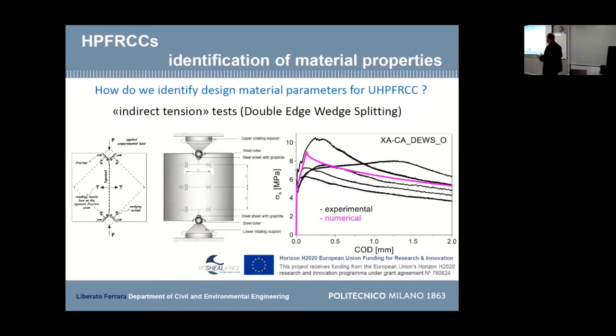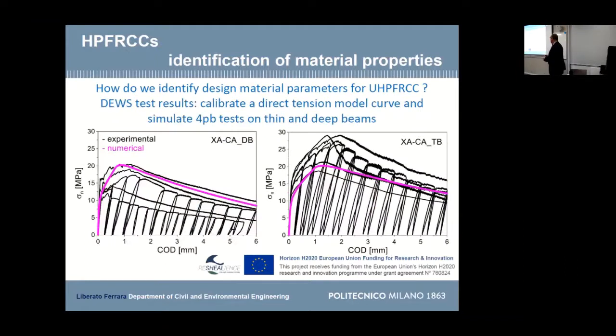And you see, these are experimental results from this test. The purple curve is the one that we identified from the bending through back analysis, through back identification based on force and moment equilibrium equations. So there is some consistency between the results. And this is the simulation. It's interesting to see that, for example, these were tests made on 100 millimeter deep beams, and our prediction was on the upper bound. These were tests made on 30 millimeter thin beams, and our prediction is on the lower bound, because in 30 millimeter thin beams with 20 millimeter fibers, all the fibers are aligned in the right direction. So you have an improvement of the performance. In 100 millimeter beams, the orientation, the alignment of the fibers is more random.